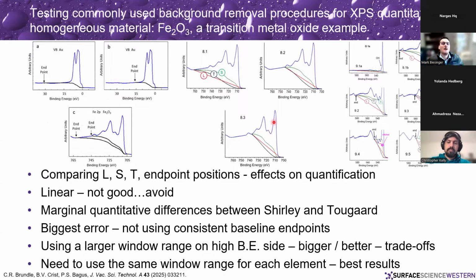This is a nice publication that came out just recently from Dick Brundle, Vincent Christ, and Paul Bagus, where they looked at iron samples or gold samples or things like that, and how good the quantification is using the different backgrounds. And again, not unsuspected, the linear just doesn't do the job properly at all. So don't use a linear background. There were really only marginal quantitative differences between the Shirley and the Tougaard background usage.